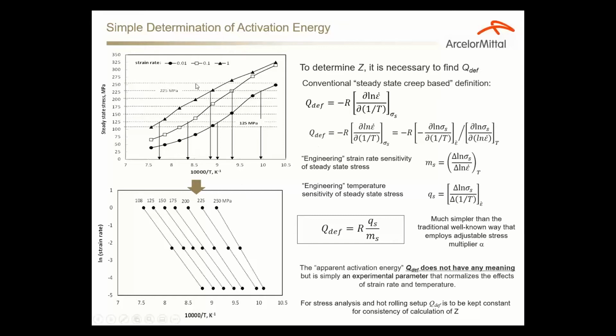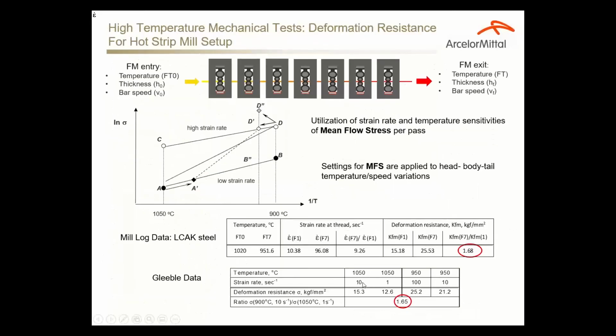So we calculate it from our test data and then give this information to the mill. They use it very quickly. Based on this, we developed what we call the four-point test procedure that allows us to predict flow stresses and hence deformation resistance, mean flow stresses, in the mill.